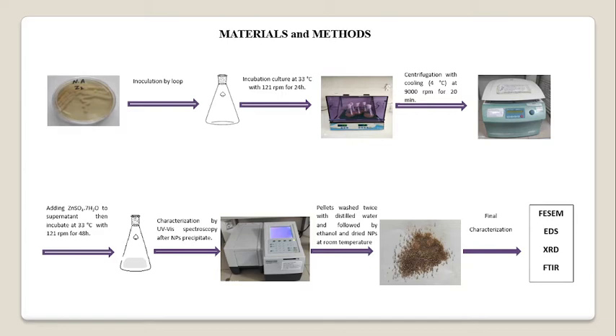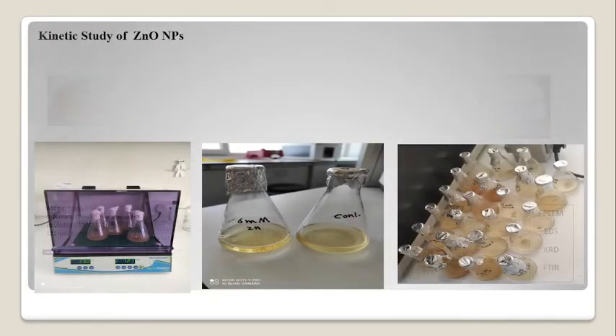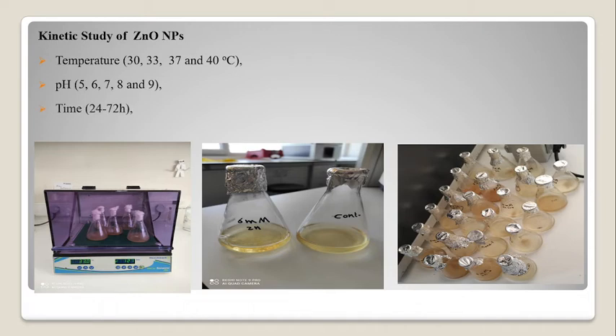After that, characterization by UV spectroscopy for precipitate. The pellets were washed twice with distilled water followed by ethanol, and the nanoparticles were dried at room temperature. After that, characterization by this device. For the kinetic study, we used different temperatures, different pH values, different times, and different precursor concentrations, from 2 to 10 millimole.